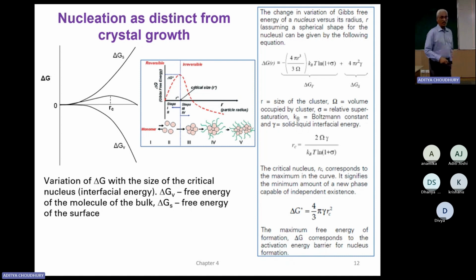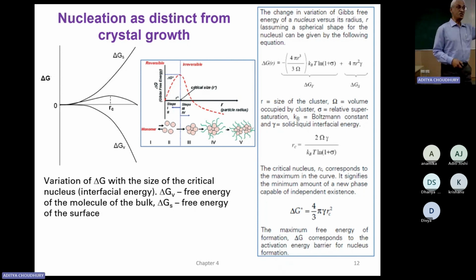It hasn't reached the critical size. So at that time, this is the delta G of surface energy, and this is the delta G of volume, the bulk. When it's really small, the surface area is large, so the surface energy is huge. So that will destabilize the formation of this kind of nucleus. Because the surface energy is very high, delta G goes up. Although due to the formation of dimer and trimer, the delta G goes down. So once it's reached the critical mass, okay, we don't know how many.